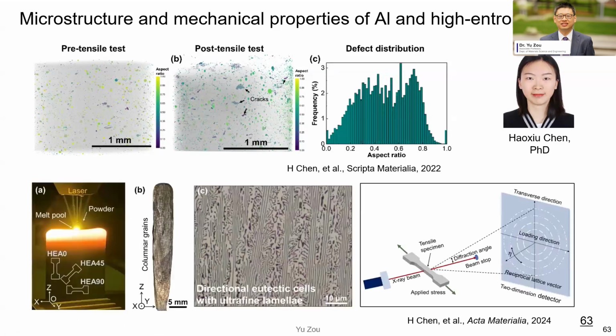And also we work on additive manufacturing of a new alloy called high entropy alloy. They showed very interesting microstructure, and then we did an in situ tensile test in a synchrotron beam line to identify how the two phases deform during the deformation process.